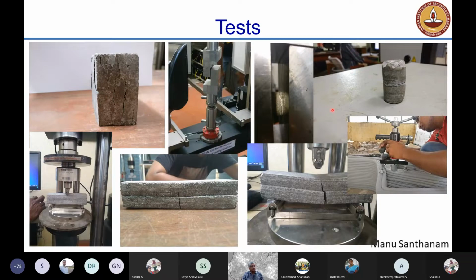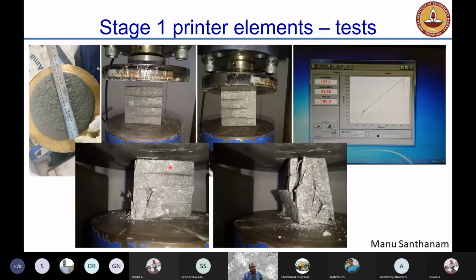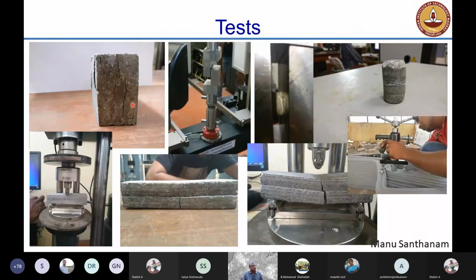This is actually a test to measure the shear capacity. So what we did was we took a core in this direction. We took a core in this direction of only about 20 millimeters and used that to then create this interface in the middle, and then we did a direct shear test on it to measure the interfacial strength.